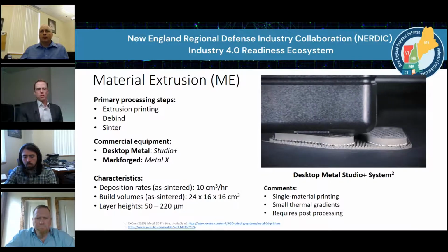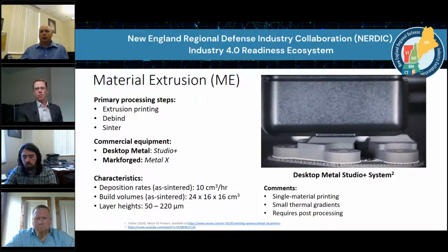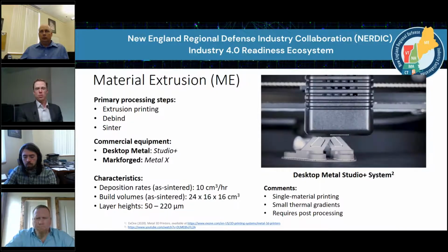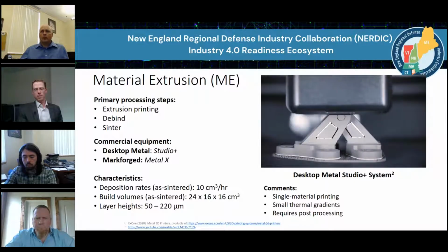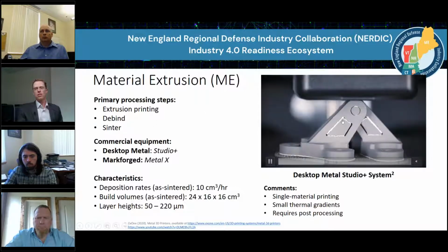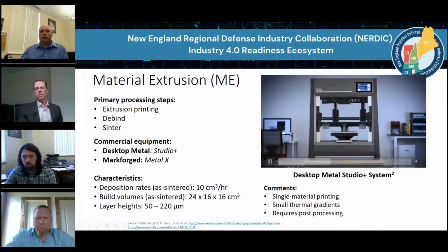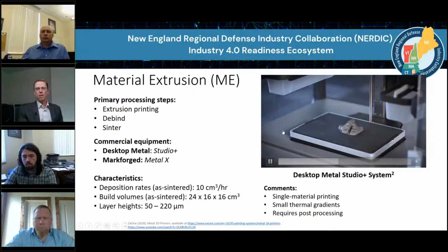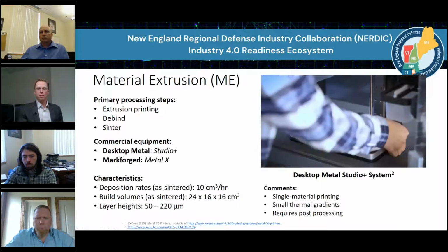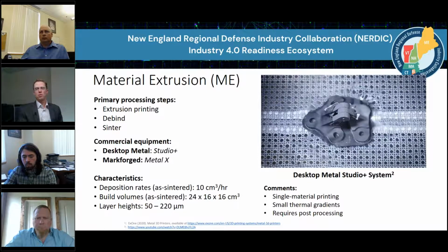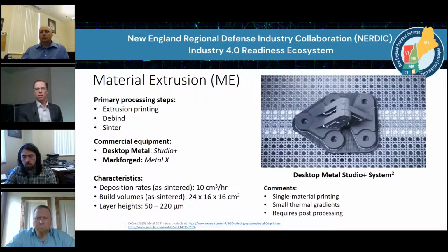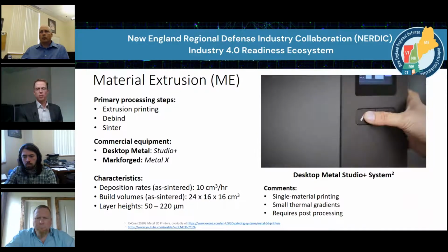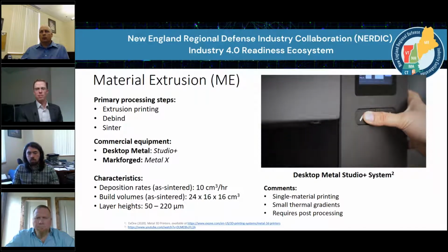So with material extrusion, the basic process as shown in the video is we first extrude out typically a binary composite of the metal and a binder, and you also see some white here for interface that goes in between there. You'll then take the part out of the printer. It goes into some sort of debinding solution, typically organic solvent. That process typically takes 48 hours or so. Obviously, this video is a little bit of time lapse.